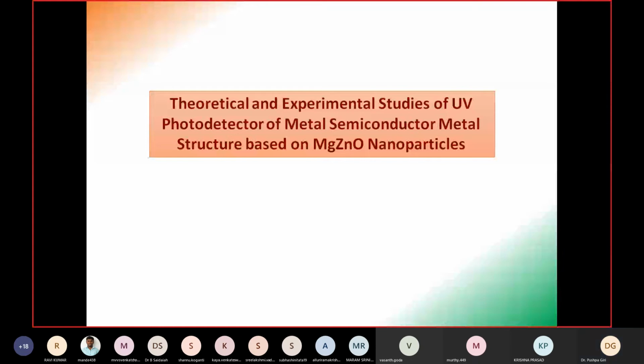We also did a comparative analysis between simple zinc oxide on silicon and 3% magnesium doped zinc oxide over zinc oxide on silicon, and how it has changed. So our grain size has been improved, roughness has decreased, and total roughness has decreased. And in the optical transmittance, we can see that transmittance has increased, reflectance has decreased, and the optical band gap has also increased. And this was the interdigitated mask.